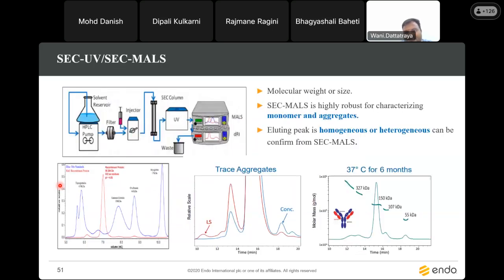Generally during this development, we have to inject some standards. Molecular weight standards we have to inject based on our molecular weights. So you will get some defined molecular weight standards and you will inject the samples. Based on this, you can determine whether there is a formation of aggregates or truncated peptides. So this we will get in the SEC-UV or SEC-MALS. Generally, SEC-MALS is the robust technique that we are using for the characterization of the formation of aggregates.